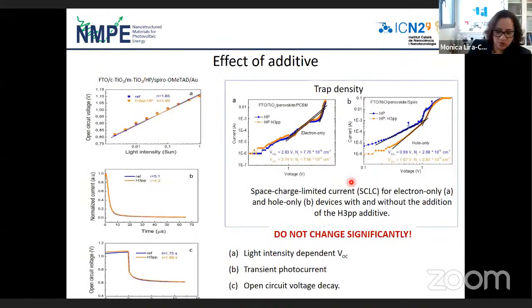We also made many other tests on our solar cells, trap density for example. We want to see the trap density we have in our devices. We made space charge limited current analysis. We also made light intensity dependent VOC to see recombination, transient photocurrent, open circuit voltage. You can see in all results there were very similar results. We were very surprised about this.